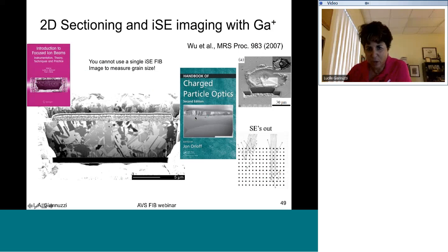And in fact, it might be hard to see here, but if you take a look at the image that's on the charged particle optics book, this is actually an image that I took. So right underneath the columnar structure, first of all, you can see a fairly large grain here in the substrate, but what you see is differences in contrast there, and that differences in contrast is due to mechanical deformation, not due to differences in grains. So what this means is that you have to be really careful when you interpret some of these images, so you have to take images at various tilts to make sure that you're looking at differences in grains versus differences in just mechanical strain or strain in the material, or just slight differences in orientation.